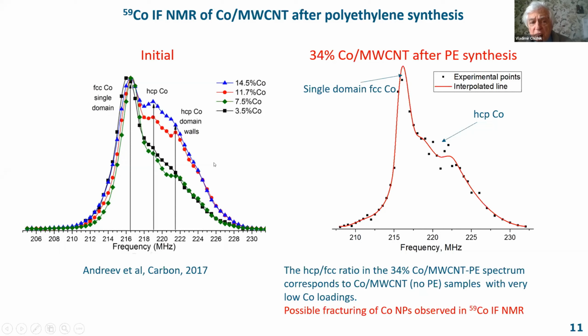But for magnetically ordered substances, there is a so-called amplification factor, which produces strong signals. What amplification factor was there for these samples? We did not measure the amplification factor, but these spectra are corrected for it by the technique where we record spectra with different powers.